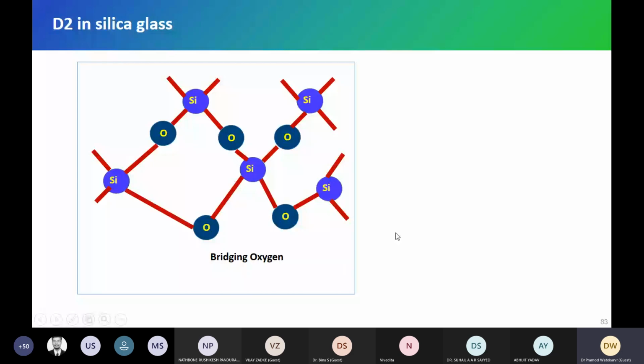And now you take it out. If you take out that bond, Si is left with O, and that O has no bonding with Si. This is called a non-bridging oxygen. So in glasses, we have a lot of non-bridging oxygen. It's a very faulty structure. Even though it's amorphous, the bonds are not correct. There's a lot of breakage of bonds, so many non-bridging oxygens are available in the glass itself.